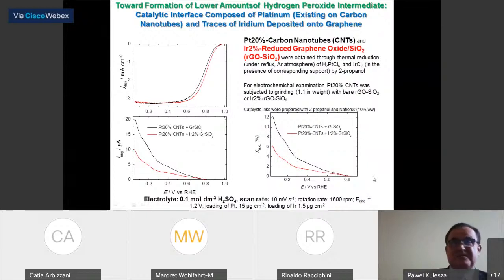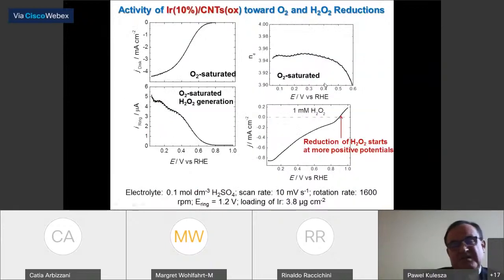The system was bifunctional or bicomponent in a sense, because iridium was on graphene. In fact, that graphene was even stabilized with some small amount of silica, but platinum was on carbon nanotubes. Later, we learned that also a combination of graphene, reduced graphene oxide with carbon nanotubes is helpful, at least from the theoretical point of view. I will not talk too much about this, but I would like to mention, showing in the right corner figure, that decomposition of hydrogen peroxide starts very early on iridium. Basically, at the moment it appears, iridium helps.